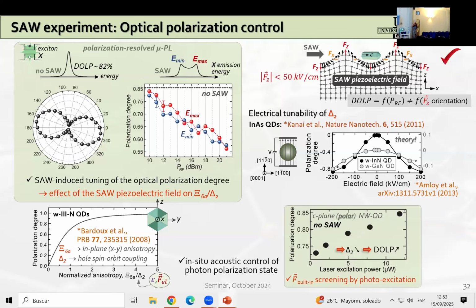And we also confirm that the origin of this behavior is the acoustic piezoelectric field by performing an experiment where we looked at the polar nanowire quantum dots in the absence of the acoustic wave. And then we see that when we increase the laser excitation power, while increasing this optical pumping, we are screening the built-in electric field which exists in polar quantum dots. And this screening of the built-in field by photo-generated carriers leads to the reduction of the spin orbit energy, and thus to an increase of the polarization degree. Now, the fact that we don't observe this effect in non-polar and semi-polar quantum dots indeed suggests that it is the piezoelectric field that is causing this behavior.